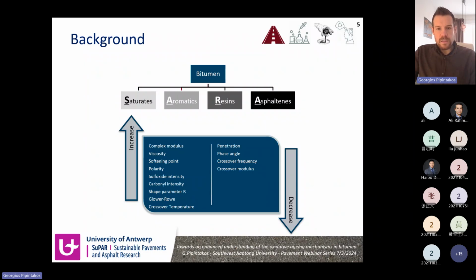Now, bitumen is the most important component of the asphalt, since it is made of organic matter, as I mentioned, and this makes it prone to oxidative aging. And for bitumen, we have used a kind of simplified way to understand the chemical fractions, the polarity-based fractions. And this is based on the so-called SARA fractions. These come from the four names of saturates, aromatics, resins, and asphaltenes, with increasing polarity, going from saturates to the asphaltenes.